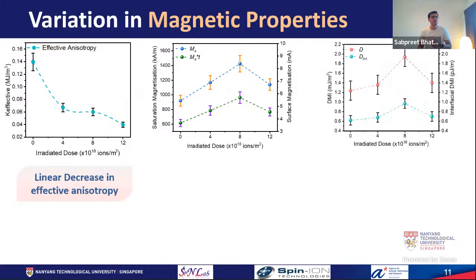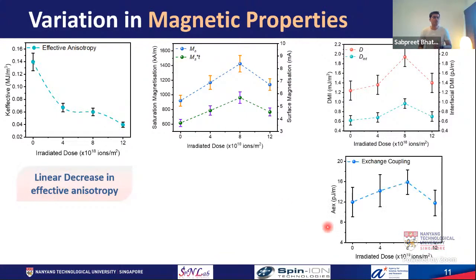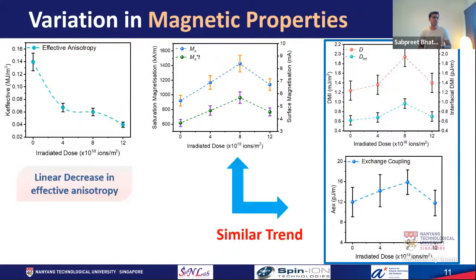And further, we have calculated the Dzyaloshinskii-Moriya interaction using Brillouin light spectroscopy, which also shows a high value at 8x. Now, for the exchange coupling, we have used micromagnetic simulations, which also show a similar trend, which was quite interesting to us, that is, how the magnetostatic energy is affecting the Dzyaloshinskii-Moriya energy as well as the exchange coupling energy. Now, we were able to see an increase in the DMI without enhancing the effective anisotropy.